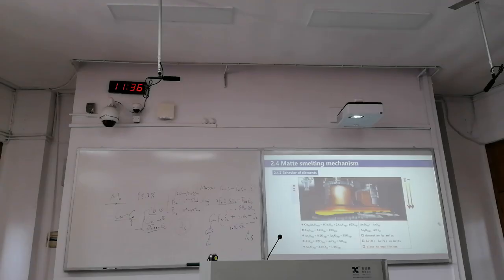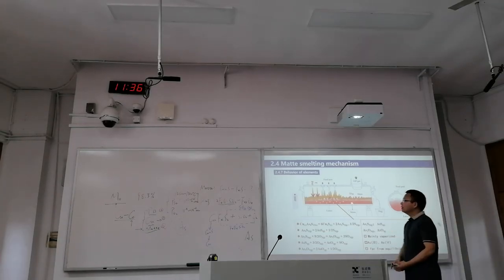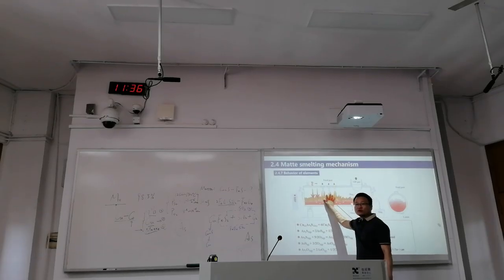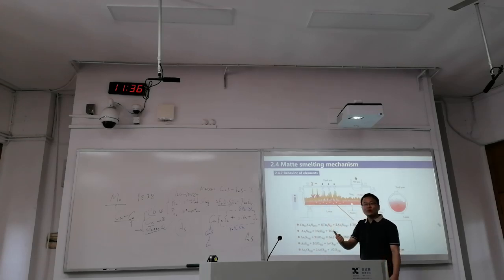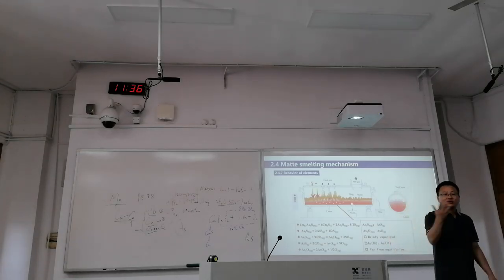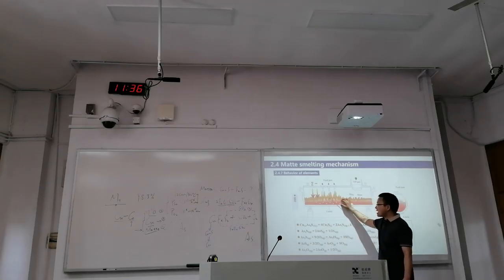And for the bottom blowing, let's check it one more time. Same reactions. In this part, concentrate is added from the mouth. Oxygen is ejected from the bottom. So oxygen is here, sulfide is here. The reaction will happen together with oxygen. Where is oxygen? Where are the oxidation reactions? Where is the energy? Where is the high temperature? So this is the sequence. We are having oxygen here, oxidation reactions here, and the high temperature here.